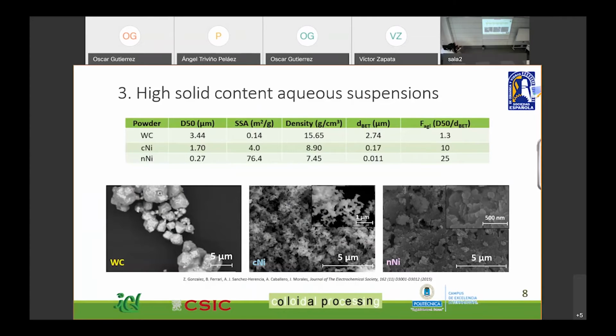So actually both of the nickel powders have a micrometric particle size, but the size of the nanometric nickel powder is much smaller. And it can also be appreciated that there is a huge difference in the specific surface, which is really big in the case of nanometric nickel. There are also significant differences in the shape of the particles. I don't know if you can see it very well, but they are kind of stick-shaped particles in the case of commercial nickel, and in the case of nanometric nickel, the particles are rounded and flat.